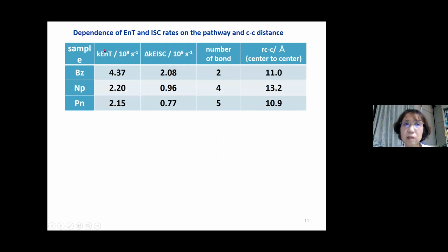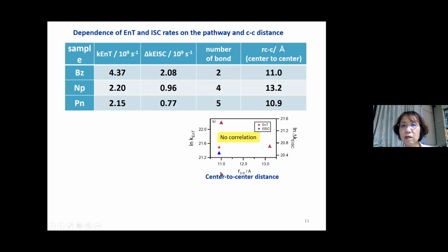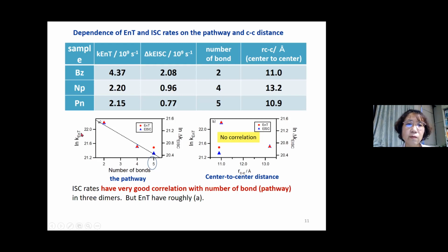So this table summarizes the energy transfer rate from the copper porphyrin to the free base porphyrin, and the enhanced intersystem crossing rate within the free base porphyrin in the dimer, and also the number of bonds and center to center distance. Now we see that if we consider the energy transfer rate and enhanced intersystem crossing rate versus center to center distance, we see no correlation. However, if we take the number of bonds that represent the pathway between the two porphyrins, it shows a very good correlation.